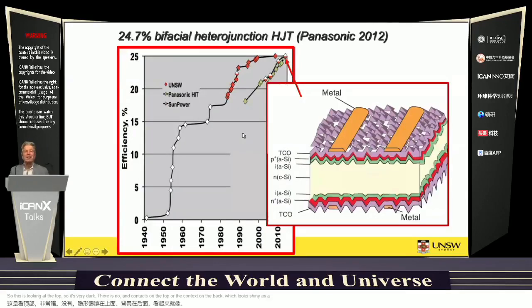all the contacts are on the back, which look shiny as a consequence. And then Sanyo, who subsequently became Panasonic, worked on this heterojunction structure called HIT or HJT, and it uses amorphous silicon with a lot of hydrogen in it, which effectively acts as a much wider band gap material than the crystalline silicon. But it was like some of the III-V technology that's used in transistors and so on, using a heterojunction approach. They got to 24.7 with that approach there.